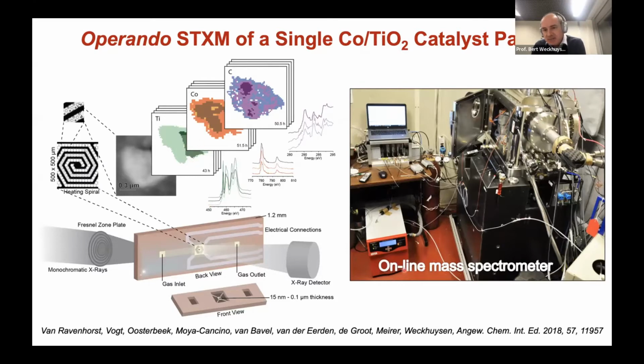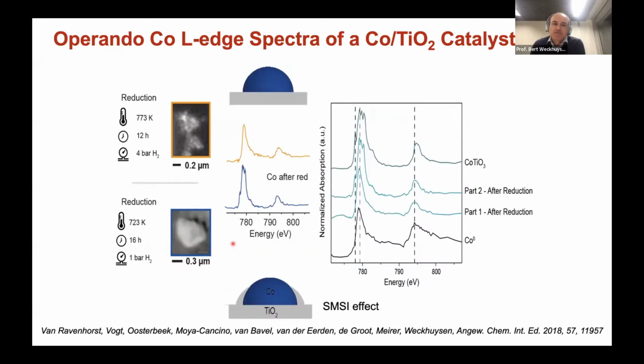The reaction happening we determined by online mass spec. We had an in situ cell to do that, which was actually a spiral system where the catalyst particle was in between these spirals of platinum. And that allowed transmission: X-rays in, X-rays out. And when the cell is thin enough, you can do this.